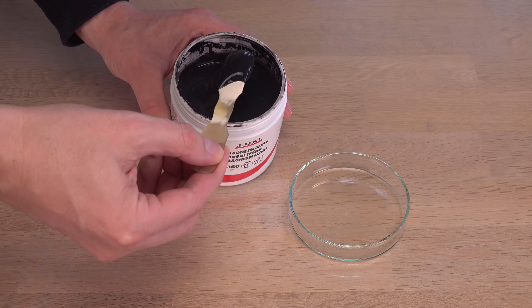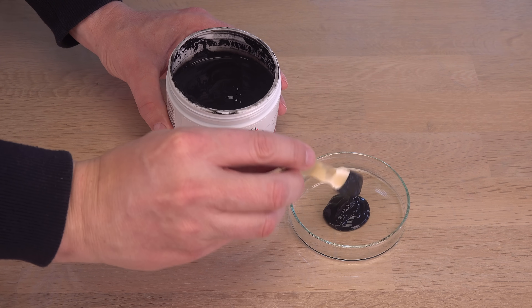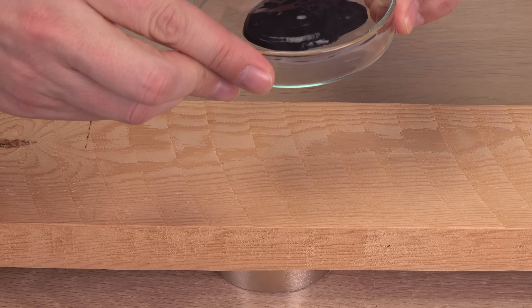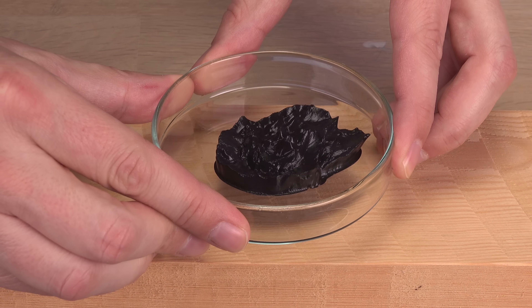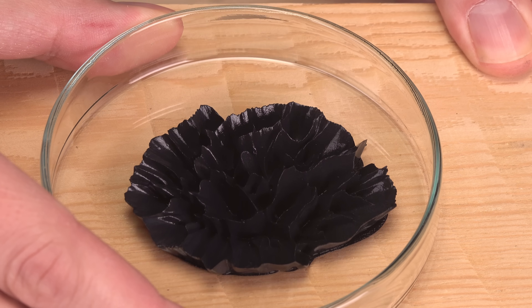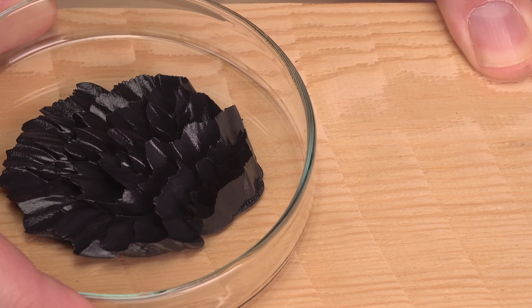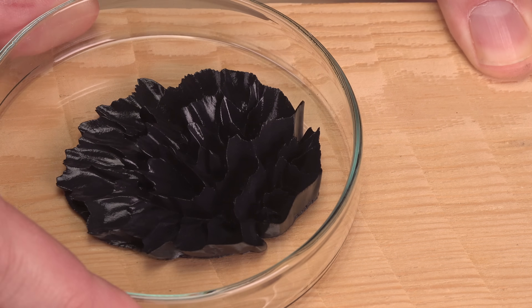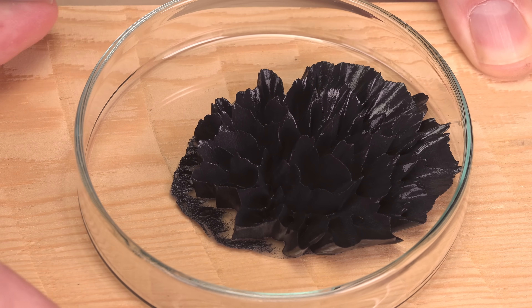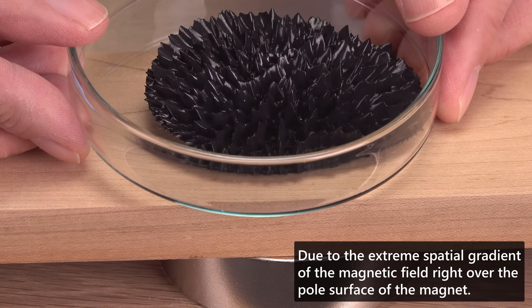Time to add more paint. In my experience, some distance is needed between the magnet and the magnetic medium for beautiful tall formations to form. I will try with 30 mm first. Nice — this is what I wanted to see. It reminds me a lot of ferrofluid: some fascinating, rich or blade-like formations in unique and changing patterns. Switching to half the distance, 15 mm, increases the number of formations but lowers their height.